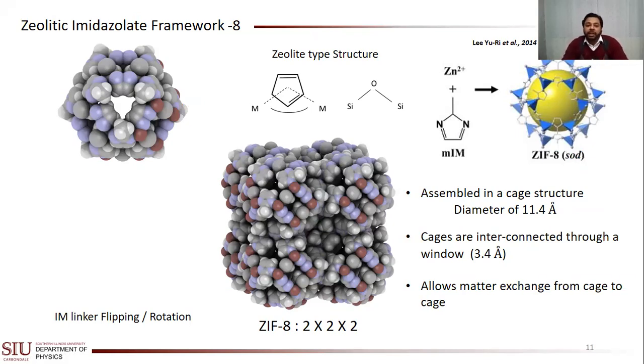Let me break down the name for you. The zeolitic part comes from the shape of the structure. It has a similar structure to zeolite or sodalite. This is a cage structure which has a diameter in each cage of about 11 angstroms, and these cages are interconnected through a window of 3.4 angstroms.